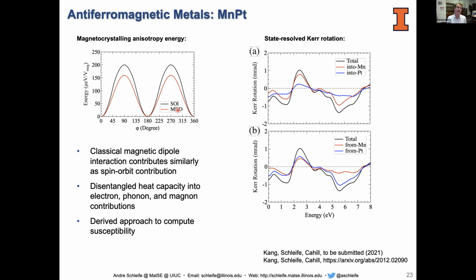Anyway, the theoretically interesting result from our current point of view is that when you look at this magnetocrystalline anisotropy energy, people typically come from ferromagnets when they study this, and they look at this contribution from the spin orbit interaction and exchange interaction. So that's the black curve. In these antiferromagnets, simply because of the energy scale of this, there's also a magnetic dipole contribution that needs to be accounted for. So that's something that Kisung in this case implemented, and for manganese platinum, we're about to submit this, and for a couple of other antiferromagnets, we have a paper in the archive.